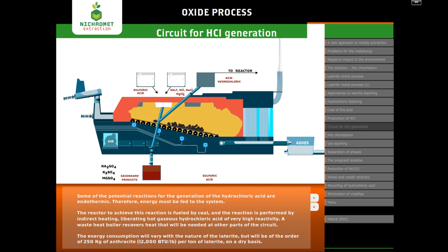The reactor to achieve this reaction is fueled by coal, and the reaction is performed by indirect heating, liberating hot gaseous hydrochloric acid of very high reactivity. A waste heat boiler recovers heat that will be needed at other parts of the circuit. The energy consumption will vary with the nature of the laterite, but will be of the order of 250 kilograms of anthracite per ton of laterite on a dry basis.